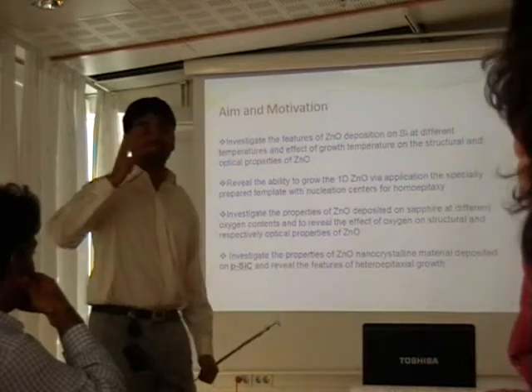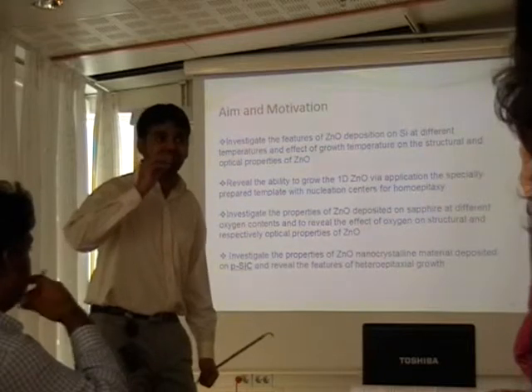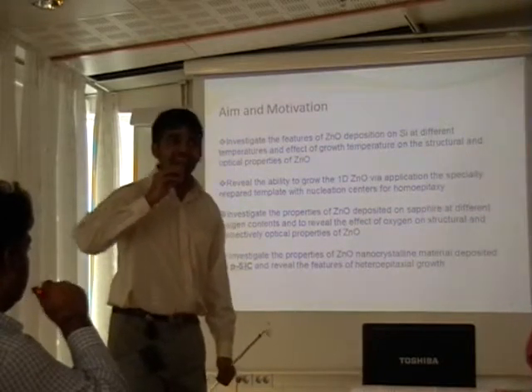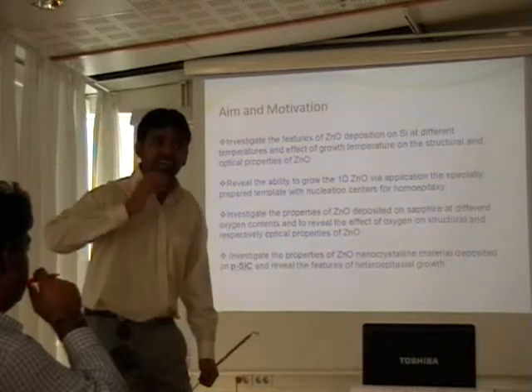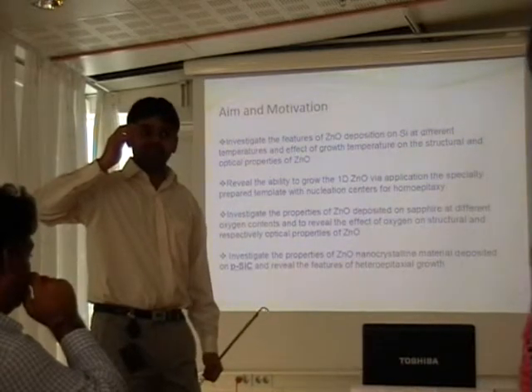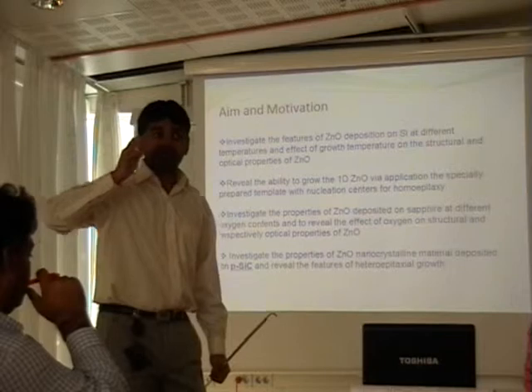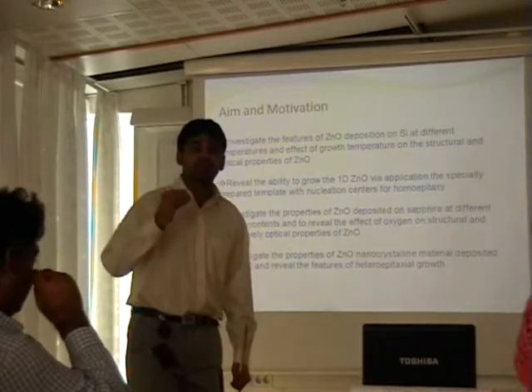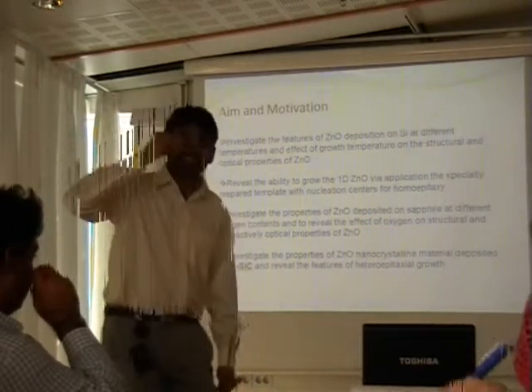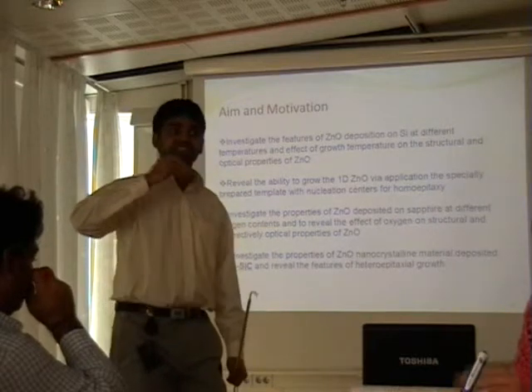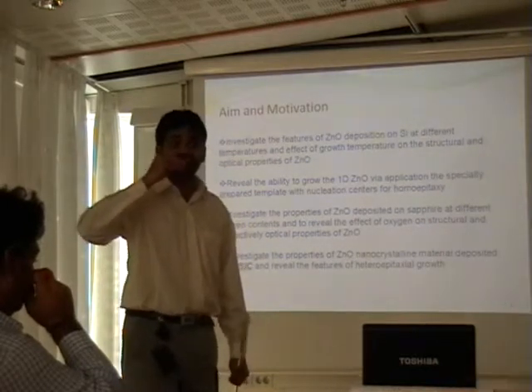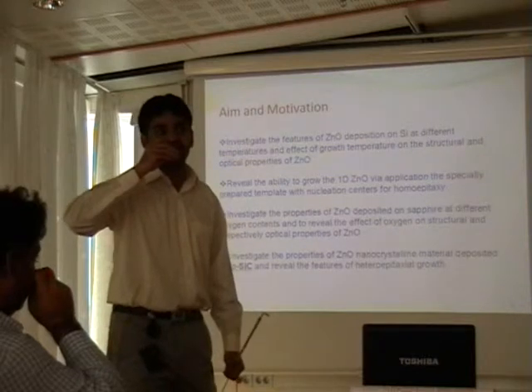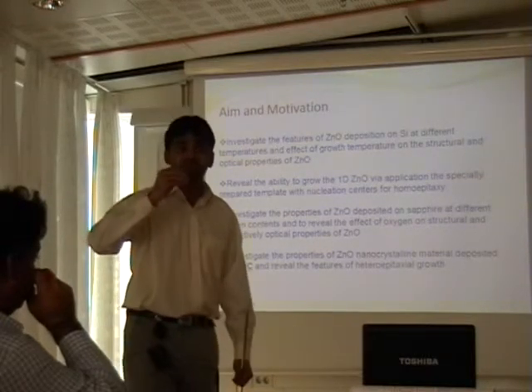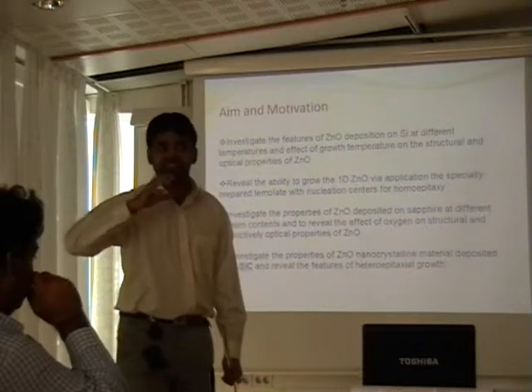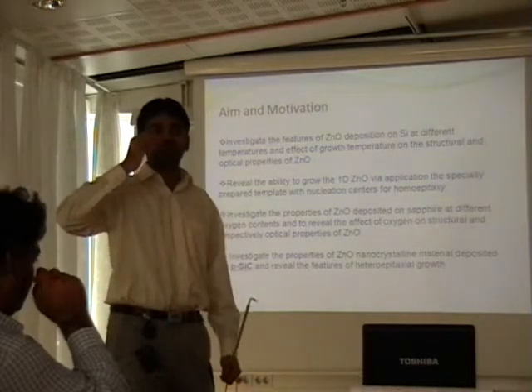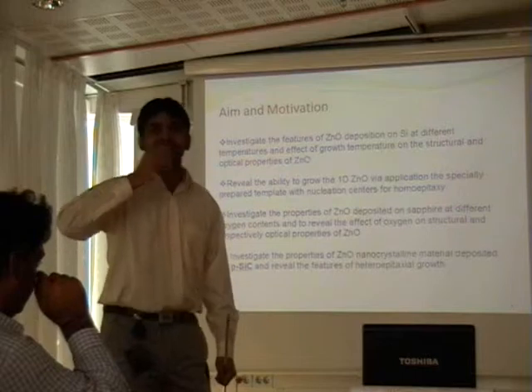There are many other substrates which have a small lattice mismatch, but they have a high cost and are not available in the market. But the problem is that growing zinc oxide on silicon is a tough task because silicon is an oxidizing material, and without using a buffer layer on it, direct growth on silicon is a tough task.